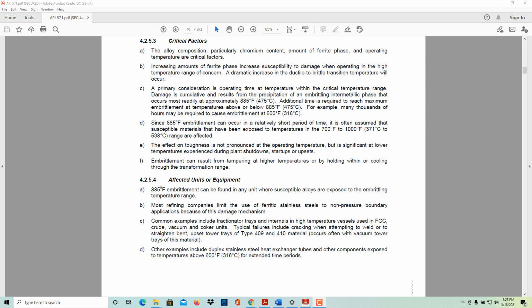Damage is cumulative and results in the precipitation of an embrittling intermetallic phase that occurs most rapidly at approximately 885 F. Additional time is required to reach maximum embrittlement at temperatures above or below 885. For example, many thousands of hours may be required to cause embrittlement at 600 F. Since 885 embrittlement can occur in relatively short periods of time, it is often assumed that susceptible materials exposed to temperatures in the 700 to 1000 F range are affected.